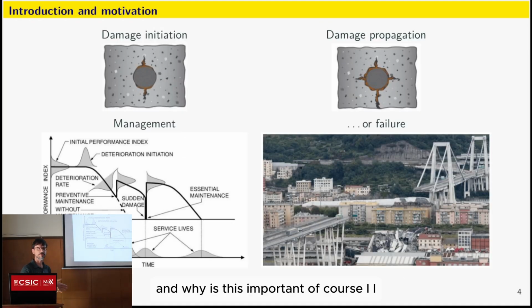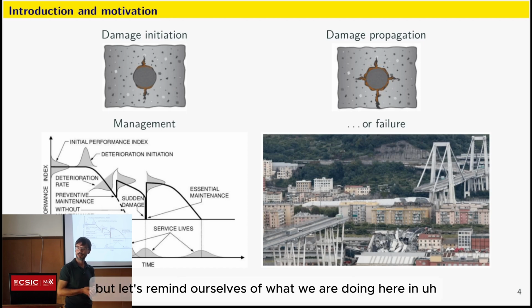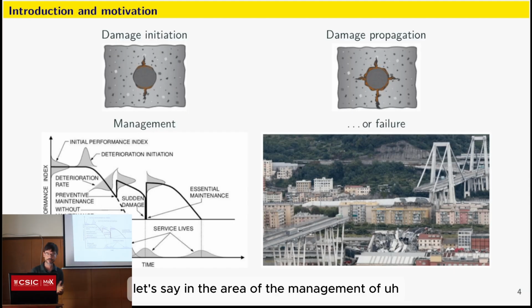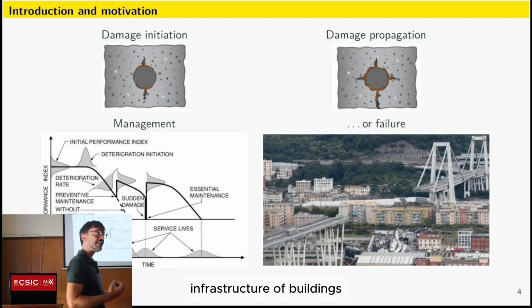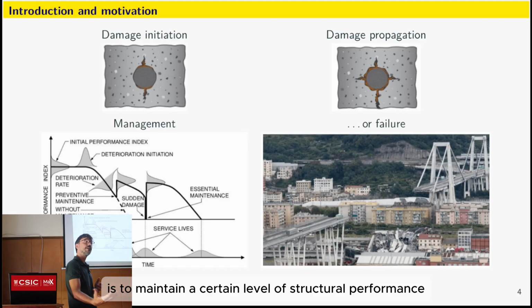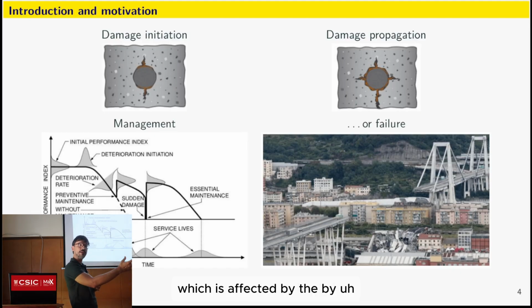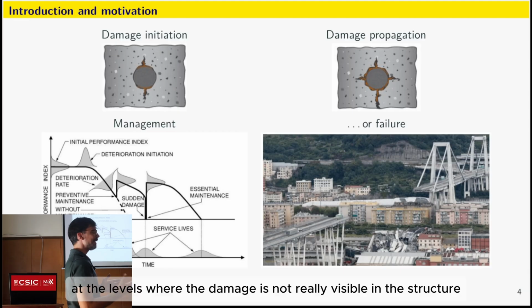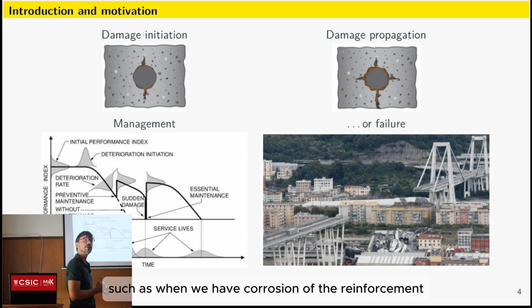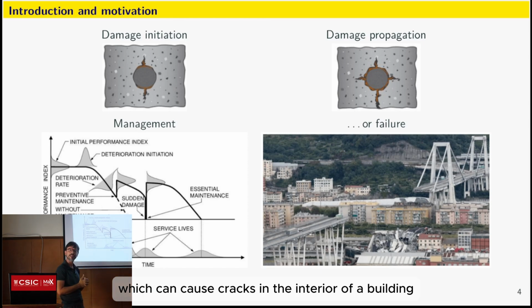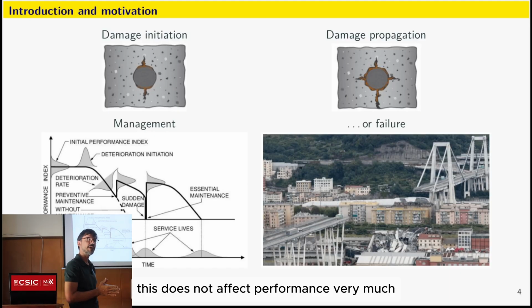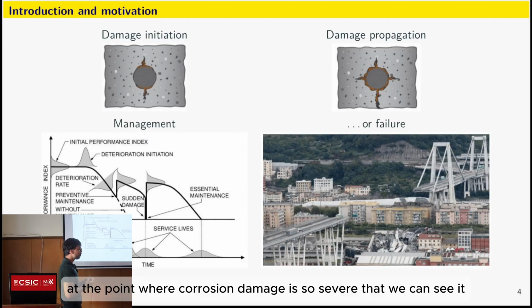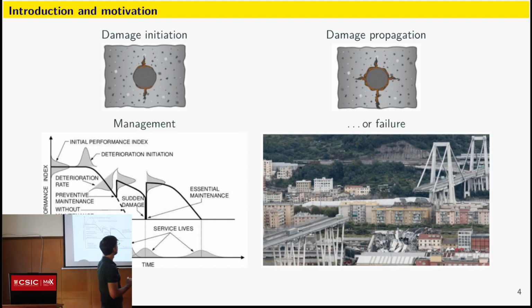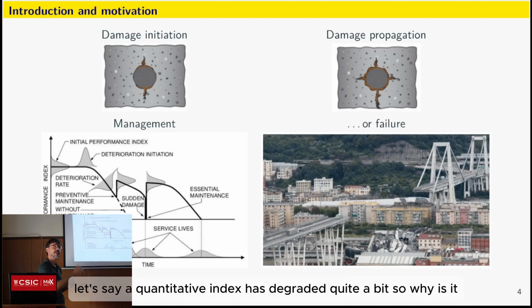And why is this important? Of course, I really don't need to tell you, but let's remind ourselves of what we are doing here. In, let's say, the area of the management of infrastructure, of buildings, what we want is to maintain a certain level of structural performance, which is affected by the onset and the development of damage. At the levels where the damage is not really visible in the structure, such as when we have corrosion of the reinforcement, which can cause cracks in the interior of a building, this does not affect performance very much, but we also cannot really see it. At the point where corrosion damage is so severe that we can see it, structural performance, let's say a quantitative index, has degraded quite a bit.